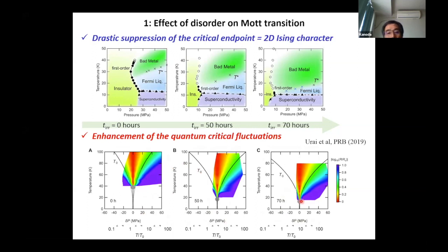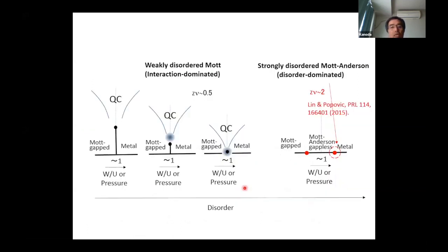Okay, and so this is the last graph. We are here, in the weak disorder regime, and the quantum critical region goes down in energies by introducing disorder. And the critical exponent Z nu of 0.5 means that this transition, the metal-insulator transition, is driven by interaction.